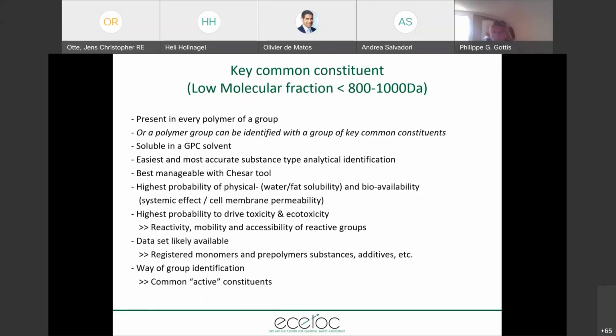It has to be soluble in a GPC solvent for easiest and more accurate substance type analytical identification, so that you can make a GPC spectrum, for instance. It is well manageable with the Chesar tool, which is, let's say, well suited for molecules with molecular weight below 800. It has the highest probability to be physically available, to be soluble in water and fat, and also bioavailable for systemic effects via cell membrane permeability.